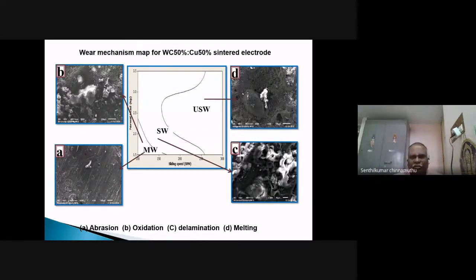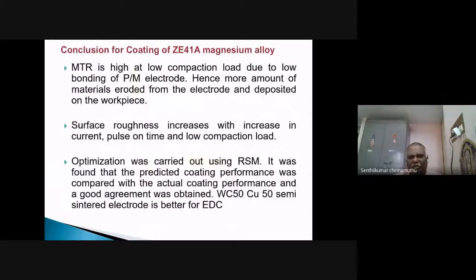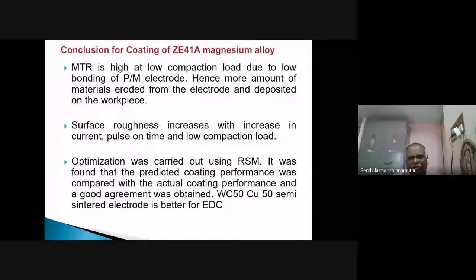The conclusion from the coating of ZE41A magnesium alloy: the metal transfer is high at low compaction load due to low bonding of the powder metallurgy electrode. More metal is deposited from the electrode. And in the case of higher compaction load, higher current and higher pulse on time, erosion takes place instead of transfer. That is, metal removal takes place. Similarly, the surface roughness increases with increase in current, pulse on time, and low compaction load.